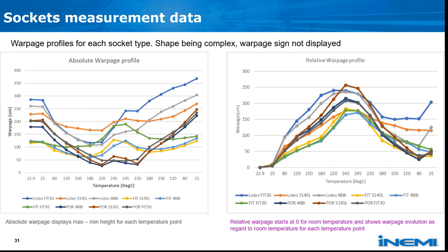So we have been measuring the different designs, different materials, and getting the absolute and relative warpage. On the left graph, we can see that the different sockets are showing different warpage values at room temperature, the far left point. And we can see that during the heating process, the warpage is decreasing, and during the cooling process, the warpage increases back. But if we need to compare all of them together, it's kind of difficult.